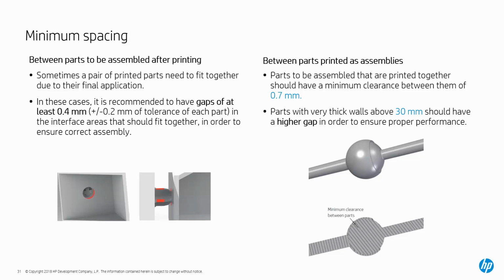If we're looking at a trapped part that's going to be a movement, depending on the thickness, but general rule of thumb is you're going to have an overall spacing of 0.7 millimeter in order for the part to be able to free up. It's not that the machine can't print a tolerance and spacing in there. It's more about the geometry of what you're doing, because if we look at the part that's on the screen for the ball joint, if we leave a smaller gap, the space will still be there, but the powder will be so compacted and we won't be able to reach blasting out the powder in order for the part to move.